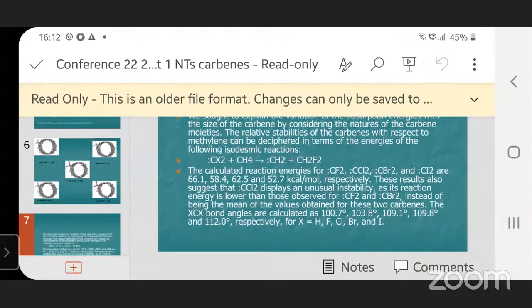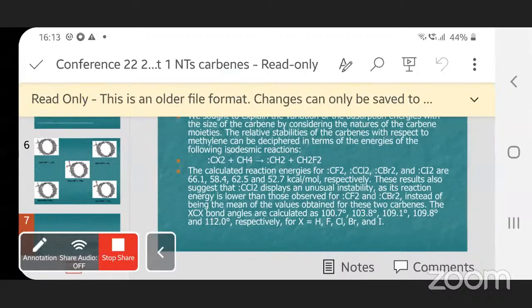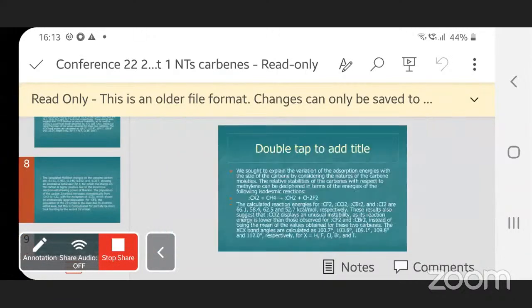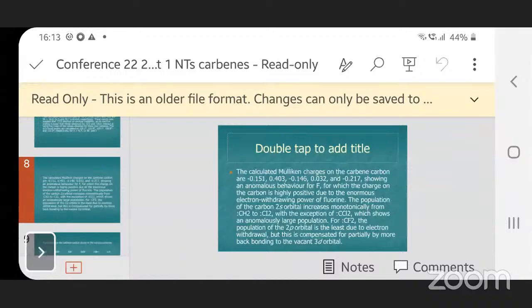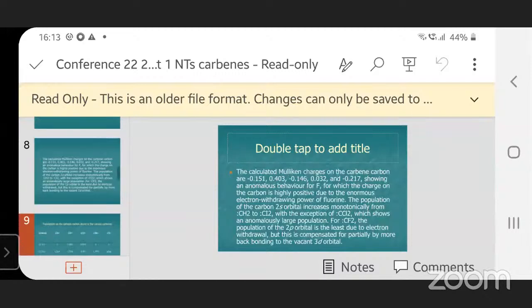The calculated reaction energies suggested that CCl2 was displaying an unusual instability. Its reaction energy is lower than those observed for CF2 and CBr2. Also one more important thing, calculated Mulliken charges reflected an anomalous behavior for fluorine, for which the charge on the carbon is highly positive due to the enormous electron withdrawing power of fluorine. So that result was slightly off balance.